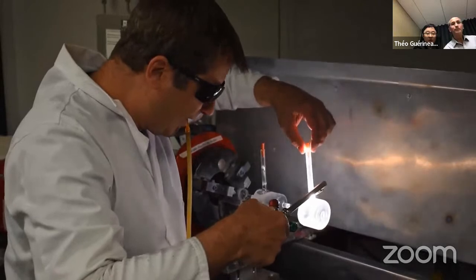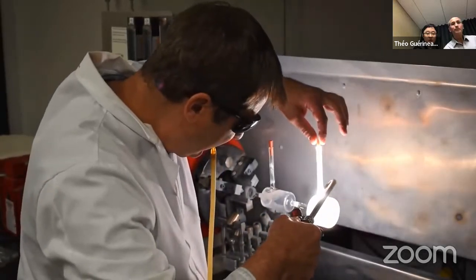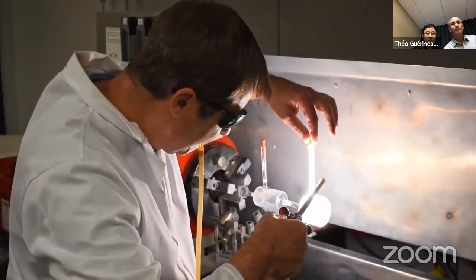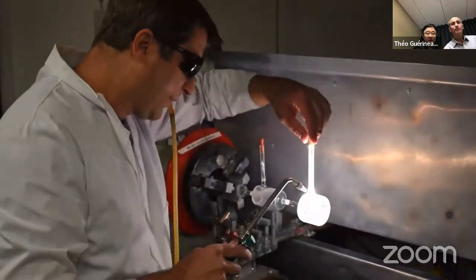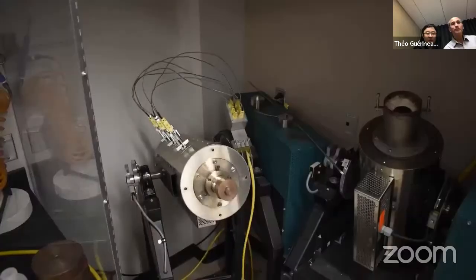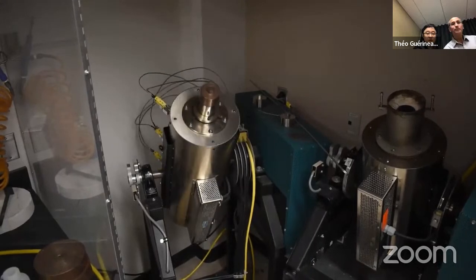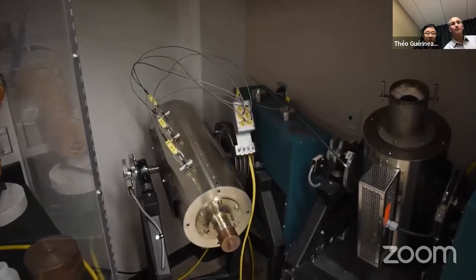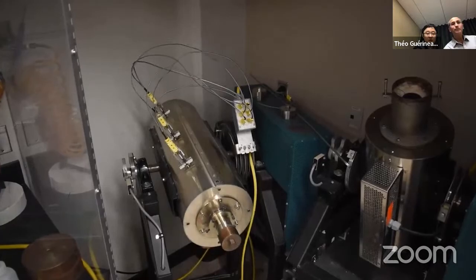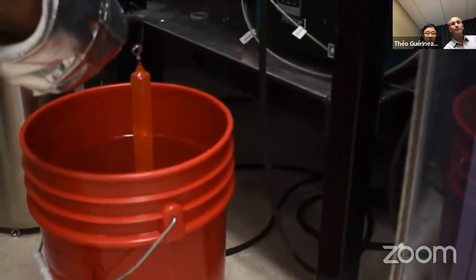When a researcher or a customer needs a glass composition, these precursors are weighed and a purification setup is assembled. The glasses are melted in a rocking furnace for several hours to guarantee their homogeneity. Each glass composition can be distilled up to 3 times to ensure its purity and transmission in the infrared region before being drawn into a fiber.